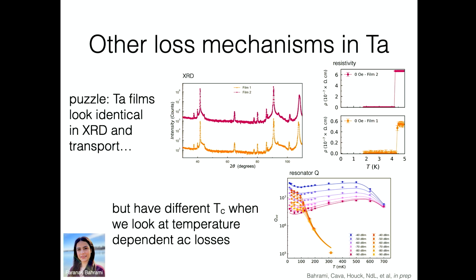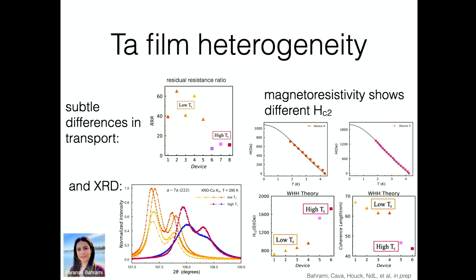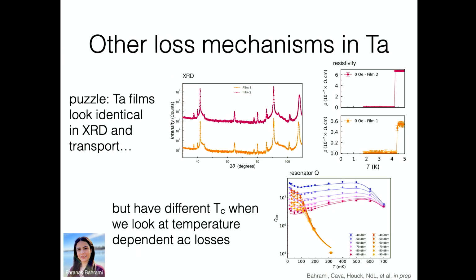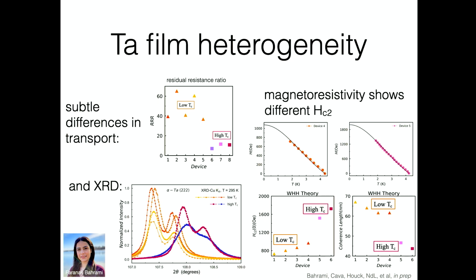Faranak Bahrami, who's a postdoc in my lab, was not satisfied that this was an outstanding puzzle. So she said, you know what, I'm going to do more materials characterization because I think you guys are screwing up. And what she found was that the fact that we see the same TC in DC transport sort of hid the fact that there were actually some subtle differences in transport. So if I look at the residual resistivity of the film, so what the resistivity looks like at low temperature right before the superconducting critical transition compared to room temperature, you actually had sort of a clumping of everything that looked like it had this exponential loss, and everything that looked good had a lower RRR.